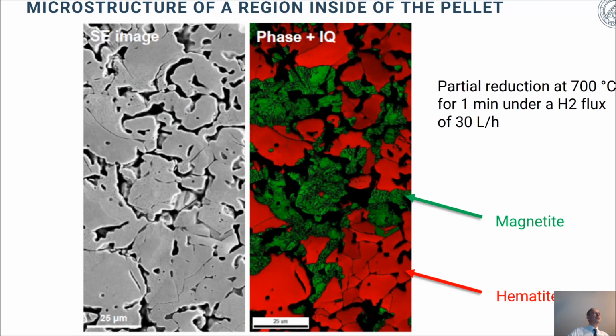So what is really interesting is to take a little look into the partially reduced pellet. And this partially reduced pellet is shown here in terms of an SE image. SE stands for secondary electrons in the scanning electron microscope. And you again see this inherited porosity from the preceding pellet manufacturing steps. And this map shows from the EBSD measurement the phase distribution and the so-called IQ, which is the image quality, which tells you how many defects you would find in each of these phases.